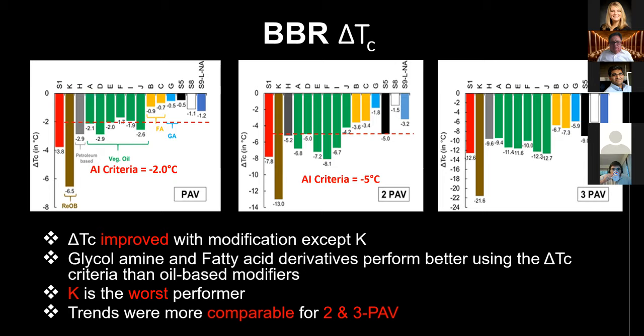The red line on the graphic of PAV and 2 PAV are the Asphalt Institute's current recommended criteria for minus 2 delta TC for single PAV aging and minus 5 for 2 PAV. Asphalt Institute has not given a criteria for 3 PAV aging because during their study that developed these criteria, they did not age to 3 PAV.